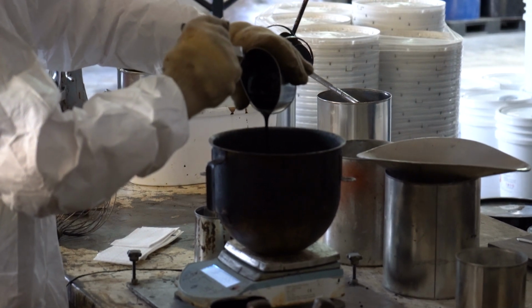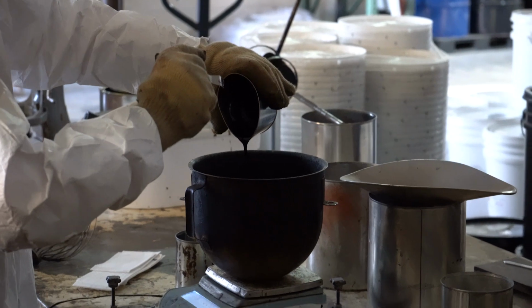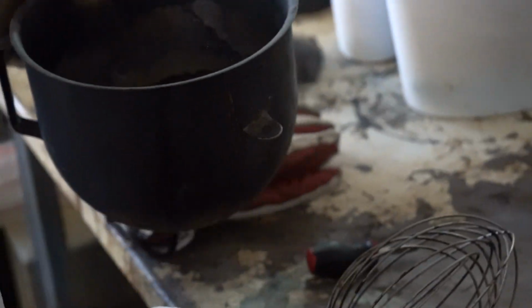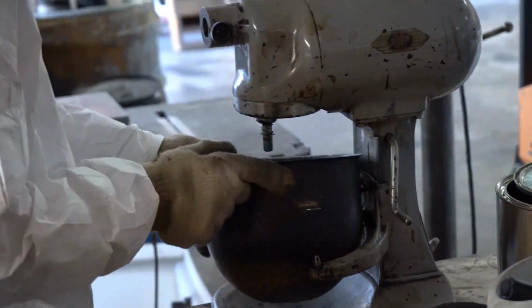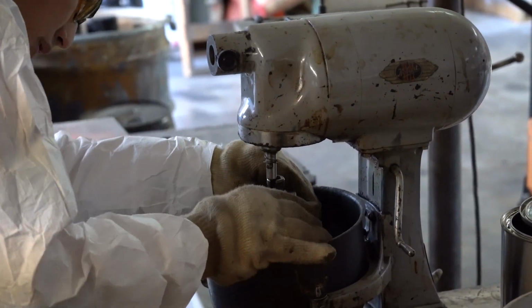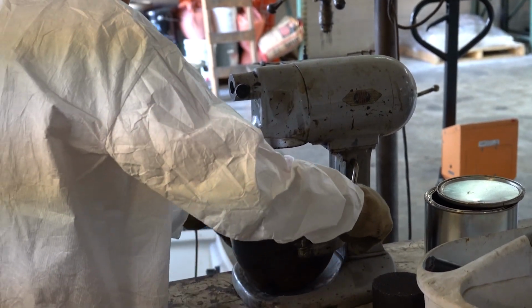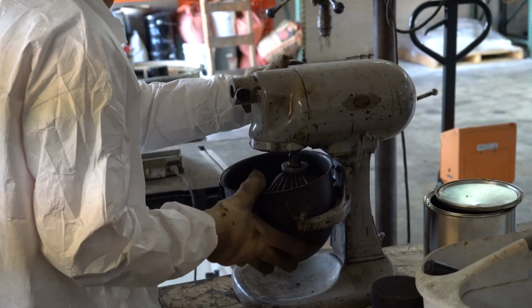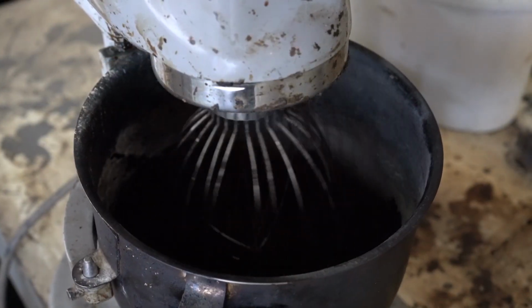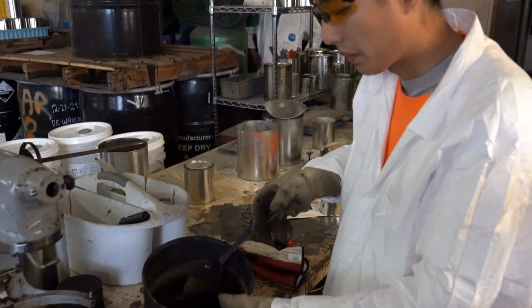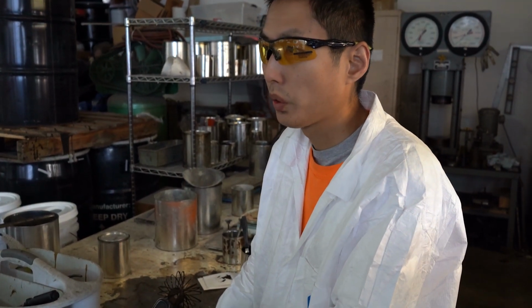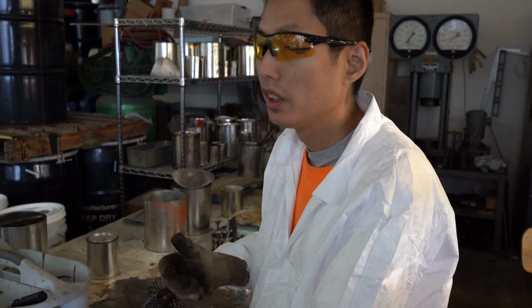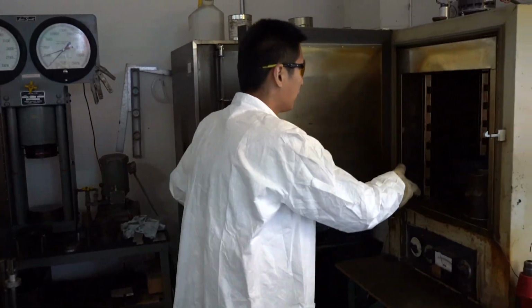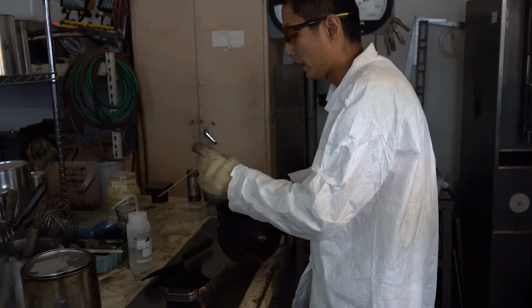Part A and part B into the hot aggregate. Okay, this is the aggregate fully mixed, and we put it into the oven at 121 C, 250 Fahrenheit to cure for about 50 minutes. Then we bring it out and we'll compact it. Take the material out after 50 minutes and I will pour it into the mold.